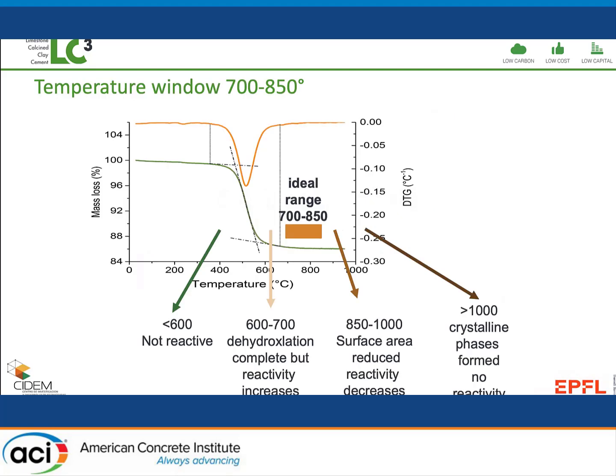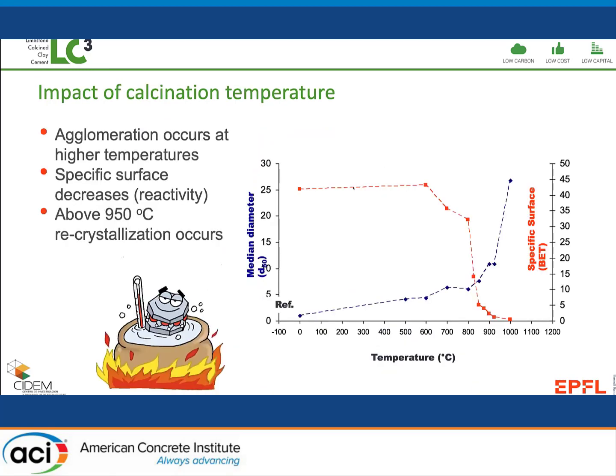So when we come to the calcination of the clay, even though the dehydroxylation takes place between 400 and 600, we find that the ideal range for calcination is more in the range from 700 to 850. And that's because we increase the disorder in the metakaolin structure, and that increase in disorder makes it more reactive. If you start going above about 850, then what you find is you tend to start getting agglomeration, the surface area goes down, and that decreases the reactivity. And if you go very high, if you go above 950, then really it's a disaster because you just get recrystallization, and then the reactivity is almost non-existent.